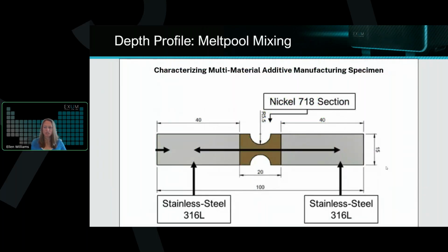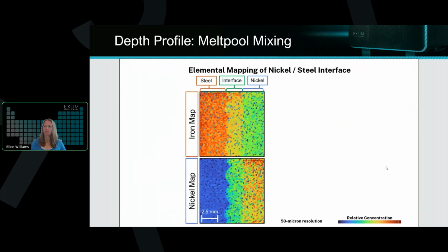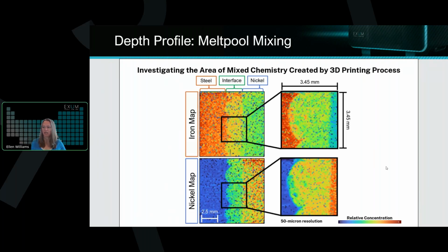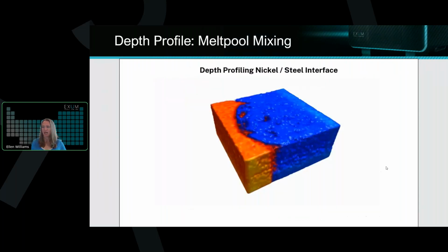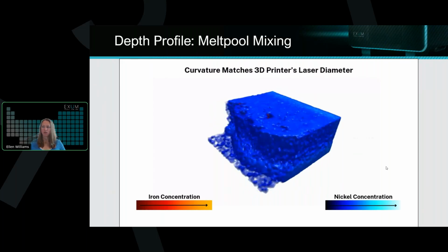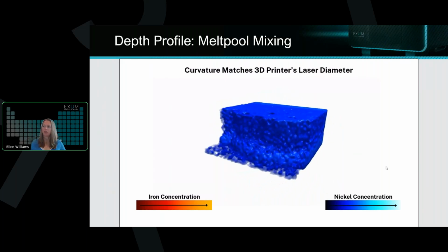And then the final piece that I want to show here is an example of our depth profiles. In this case, we've analyzed the other side of the tensile bar, where you can see the steel on the left and the nickel on the right. Again, we're looking at an area where we're able to see that curvature representing that melt pool mixing, consistent with the size and the shape of the DED laser. What we did was we analyzed a 3.5 millimeter by 3.5 millimeter area. We repeated that for multiple layers until we got through about 10 microns of material.